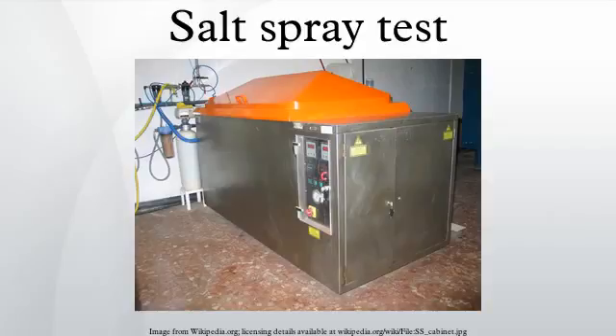ASTM G85 Annex A3: seawater acidified test. This test can be used to test the relative resistance to corrosion of coated or uncoated aluminium alloys and other metals, when exposed to a changing climate of acidified synthetic seawater spray, followed by high humidity, both at an elevated temperature. This test is also referred to as a SWAAT test.